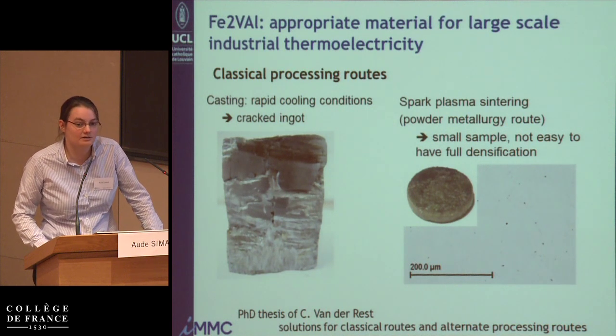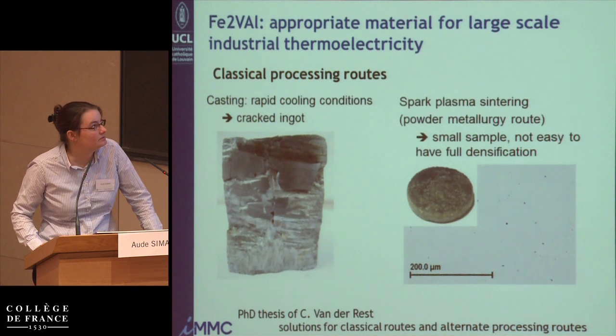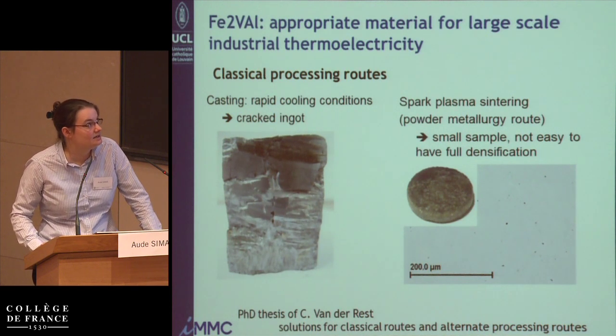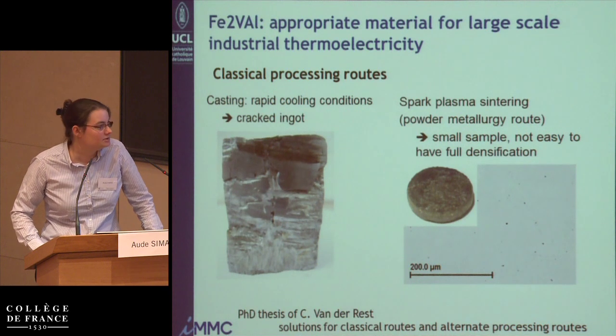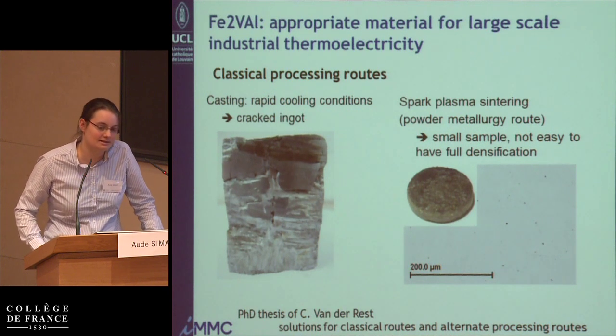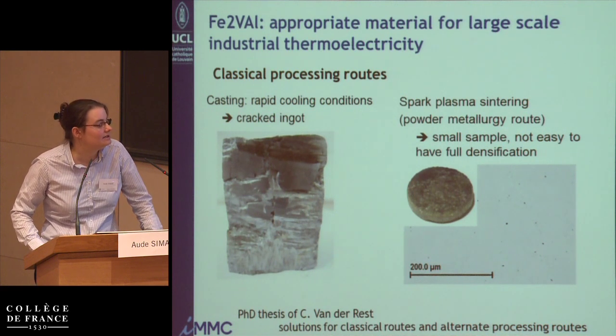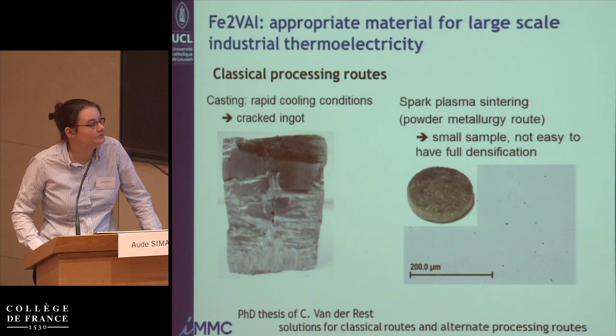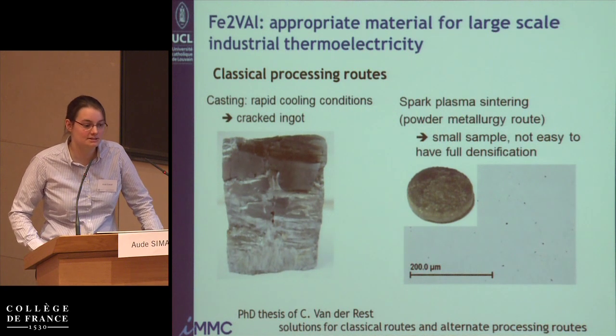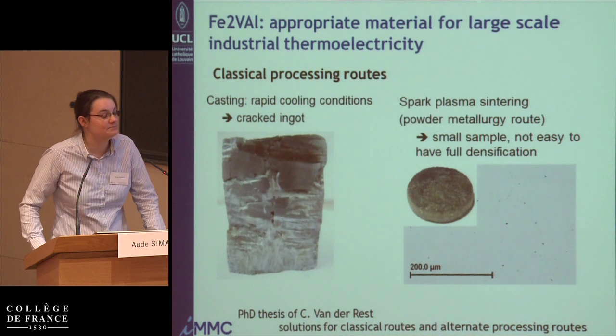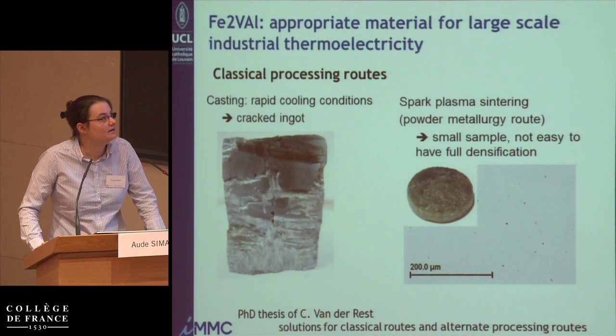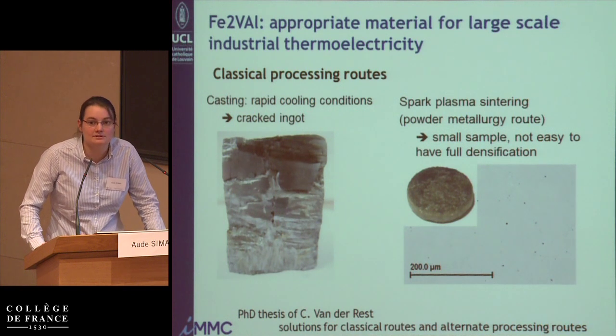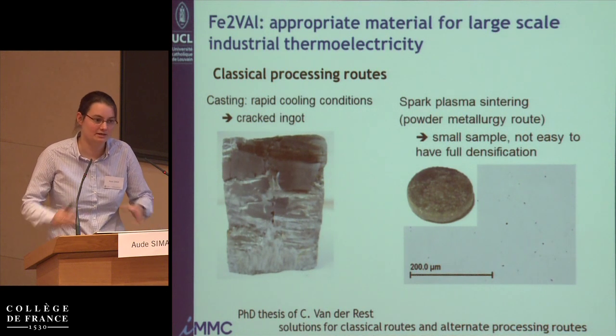We try to make materials out of that, and so we use the classical processing route like casting. So the rapid cooling condition brought us to crack ingots, and so we controlled that, but that was a hard task, controlling the rapid cooling, and so we went into spark plasma sintering, and there we have very interesting densities. It worked quite well. We also went into reactive spark plasma sintering using the elemental powders. But the problem is the size of the samples, and well, this is a rather expensive process for making a lot of materials.